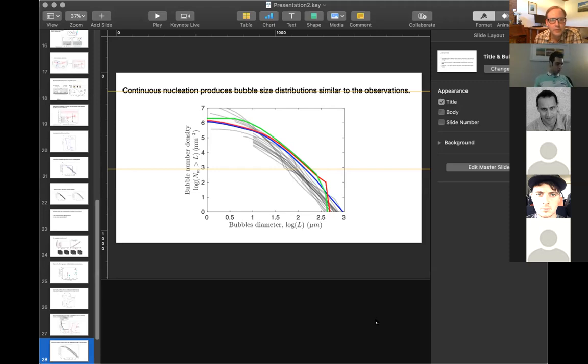That's an excellent question. What matters in terms of bubble nucleation is that there are enough magnetites for each bubble. Basically, the number density of magnetites is similar to or higher than the bubble number density. There are some interesting observations recently by Mujin et al. that observed magnetite nanolites down to 1 nanometer and also larger, with number densities way more than bubble number density, 10 to the 23 or so per cubic meter of melt. This is not tested for any of the eruptions that I studied here, but that suggests that magnetite might be present at nanoscales at much higher number density than bubbles. And that remains to be tested.